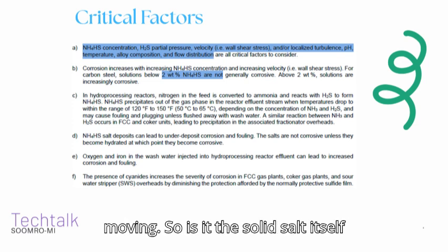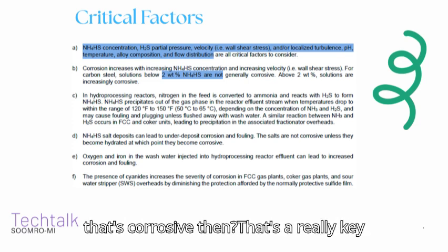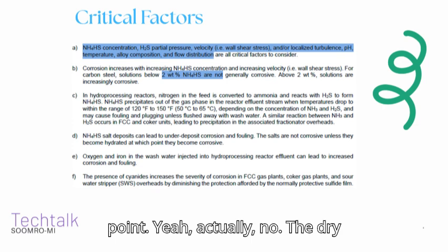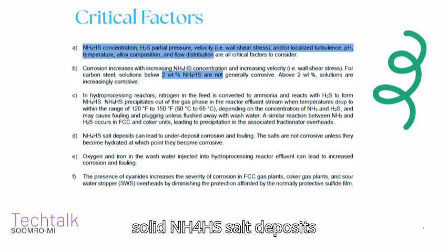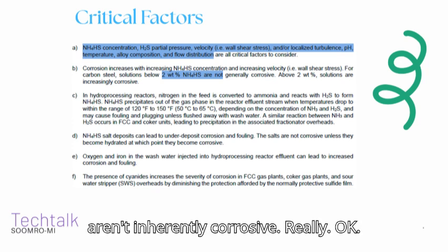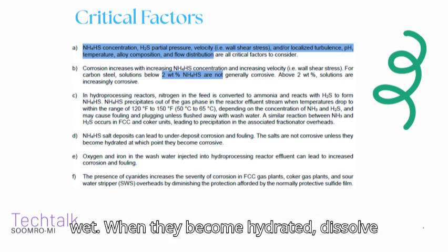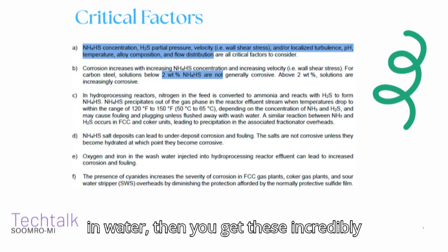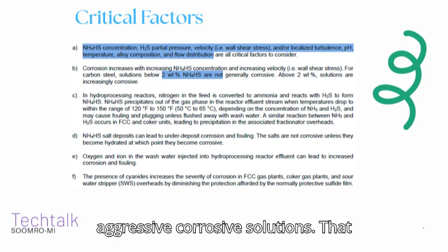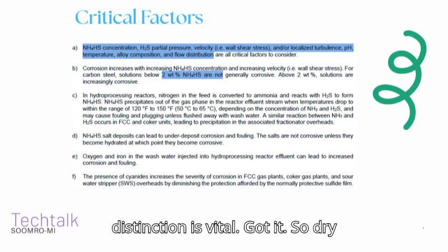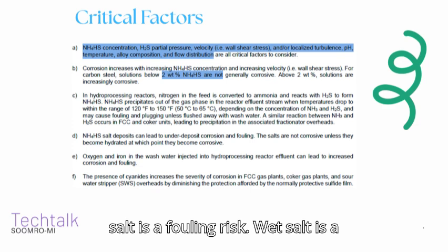So is it the solid salt itself that's corrosive then? That's a really key point. Actually, no. The dry, solid NH4HS salt deposits aren't inherently corrosive. Really? Okay. They only become corrosive when they get wet. When they become hydrated, dissolve in water, then you get these incredibly aggressive corrosive solutions. That distinction is vital. Got it. So dry salt is a fouling risk, wet salt is a corrosion nightmare.